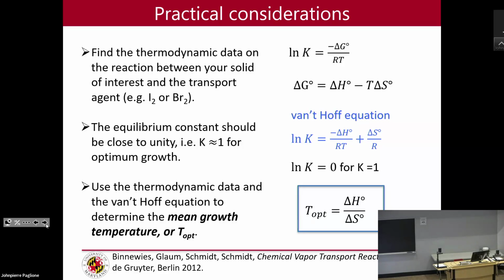So you can look up the standard enthalpy and standard entropies of your reaction, and then from there you can back out what the crystal growth temperature should be. Now, of course, you want a temperature gradient, so you want to play around with maybe -25, +25 for the two different zones in your furnace, and then that will optimize some transport.